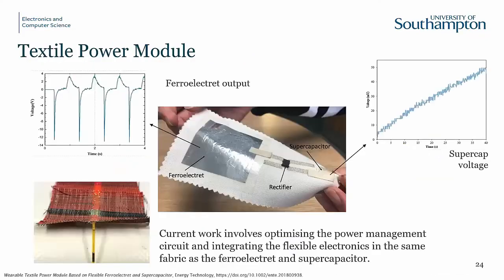So the obvious thing to do then is to combine the two, the energy harvesting with the energy storage. And again, this highlights the flexibility and the ability to just take any textile. For that supercapacitor process, for example, we've used silks, we've used polyester cottons, etc. Here, this is a polyester cotton substrate, and we're combining the supercapacitor located there with the ferroelectret. This is where we've used the textile as the mechanical spacer. If you compress that part of the textile, you generate electricity and then go through a simple rectifier and charge up the supercapacitor. So this works.